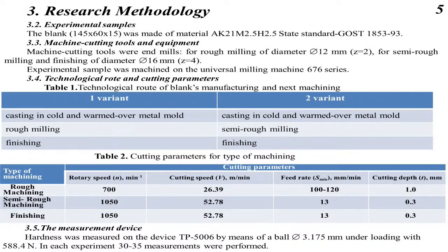COVID stopped our experimental research, but we only used aluminum alloy for casting. Castings were machined by end milling, and you can see two variants of technological routes, and you can see cutting parameters in table 2. Hardness was measured on the device TP5006 by means of a ball with diameter 3.175 millimeters under the loading 588.4 Newton in each experiment. 30-35 measurements were performed. Next slide, please.